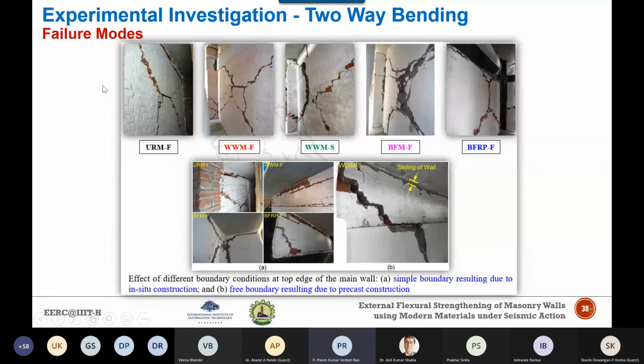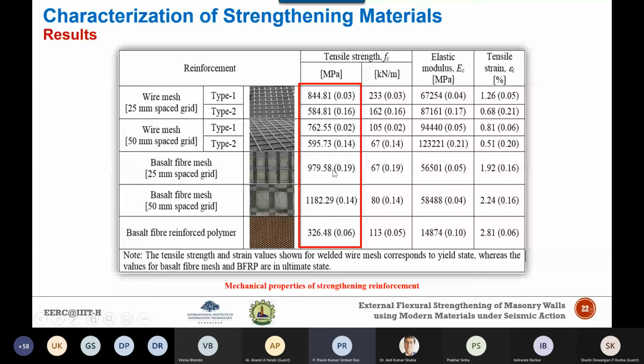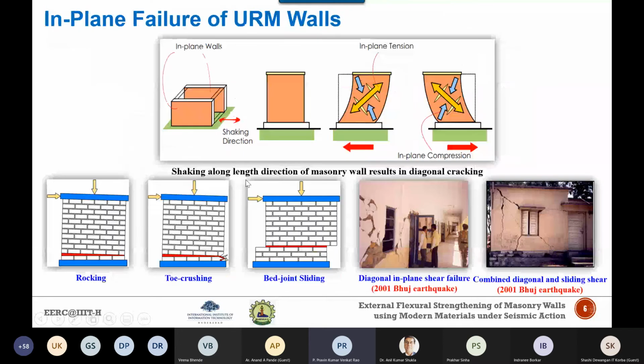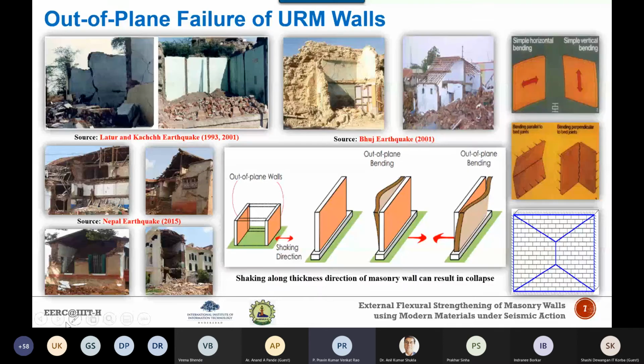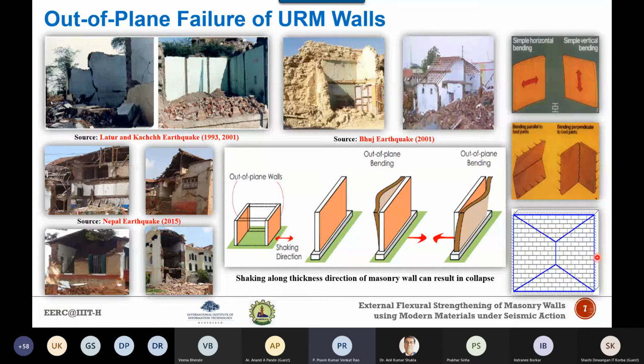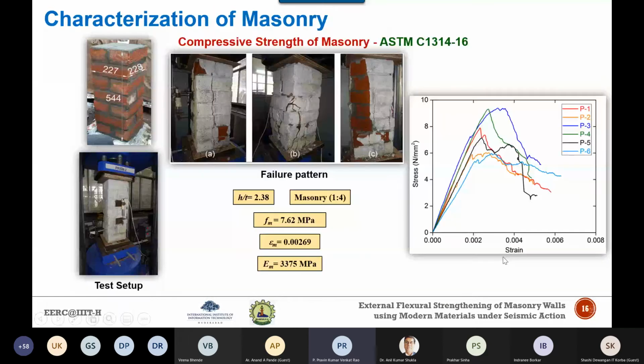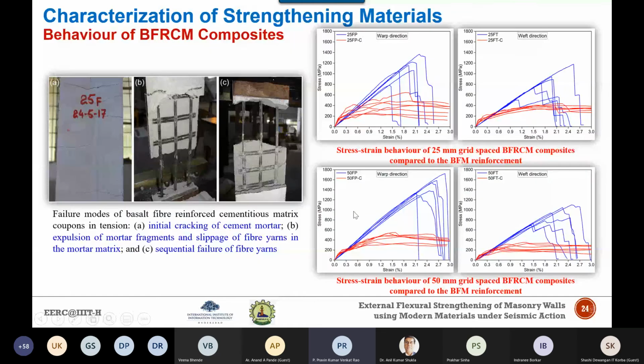This is my case of two-way bending, where all 4 edges are restrained. So there will be vertical cracks, and a combination of horizontal cracks along with diagonal crack patterns, and they almost all appear near the corners. Similarly, in the real test also, we saw a similar kind of cracking pattern.